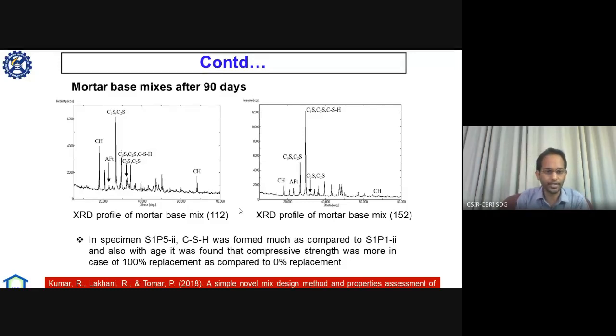And if we see the microstructural properties, we have seen that when we replaced the fine aggregate with 100% stone slurry, the intensity was more as compared to control conventional concrete, that is, no stone slurry. CSH is the major phase generated in the cementitious system, and it imparts the 7 days and 28 days strength properties. So we have seen that CSH was formed more in the case of 100% replacement, and that's why compressive strength for 100% replacement was more as compared to 0% replacement.